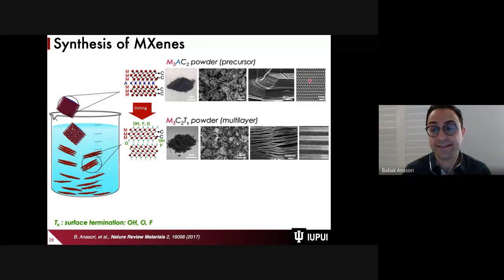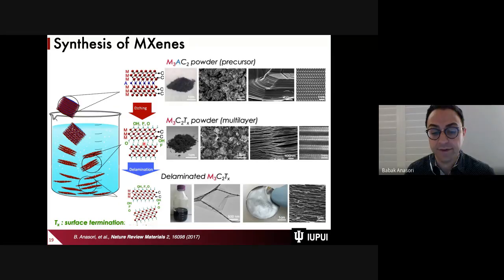Before we had just layered, but now we have this separation, and the only bond between these layers is secondary bonding, meaning OH, hydroxyl hydrogen bonding, or van der Waals bonding. Now, when we have weaker secondary bonding, it is possible to break these bonds and form 2D layers.